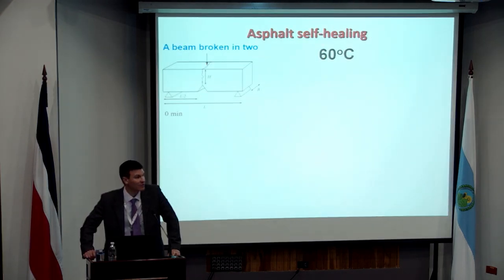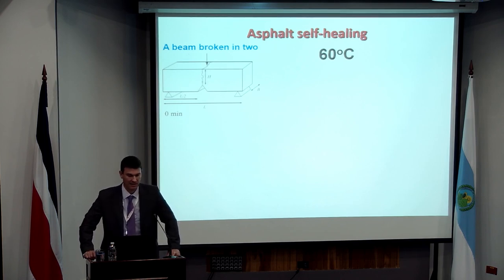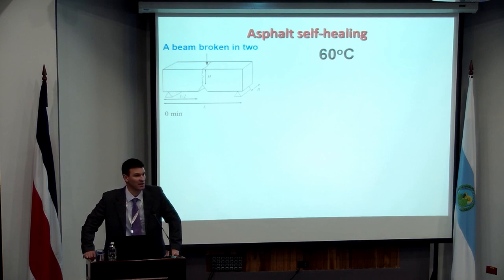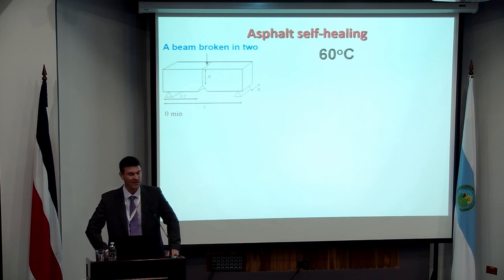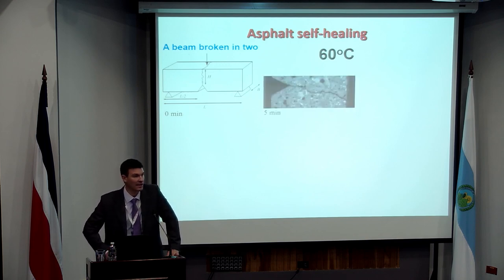We know that asphalt heals on its own anyway. So this was an experiment that we did right at the beginning. We took a beam specimen, we notched it, and we did a three-point bend test to fail the specimen in terms of complete fracture. We then placed the failed specimen back into a mold, so those two failed interfaces were together, placed it in a 60 degree C controlled environment, and then periodically looked at what's happening with that particular fracture or crack.